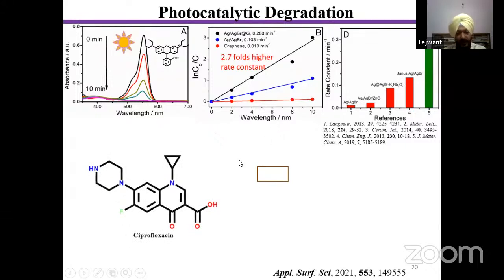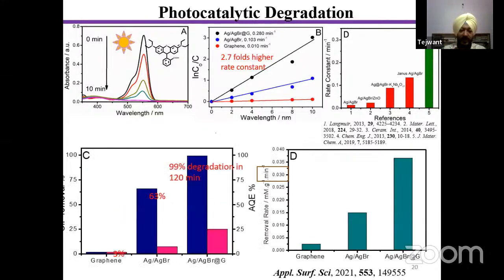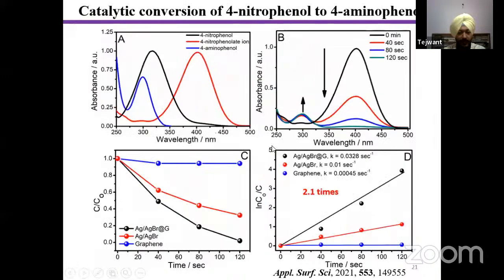Similarly, the antibiotic ciprofloxacin, which comes as bio waste from hospitals or other institutes and pharmaceutical industries, has been degraded under sunlight again. And here 99% degradation of ciprofloxacin has been obtained within 2 hours, where the apparent quantum yield has been found to be quite high in the presence of graphene as compared to the bare silver bromide nanoparticles. Okay, I'll skip this slide.